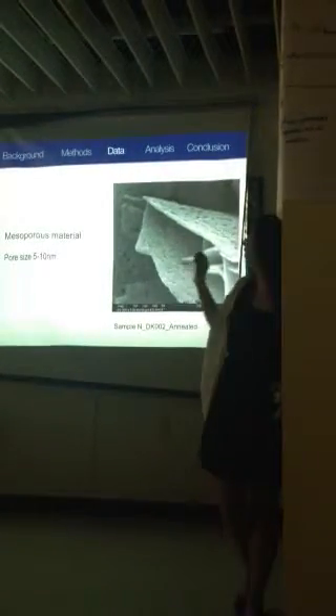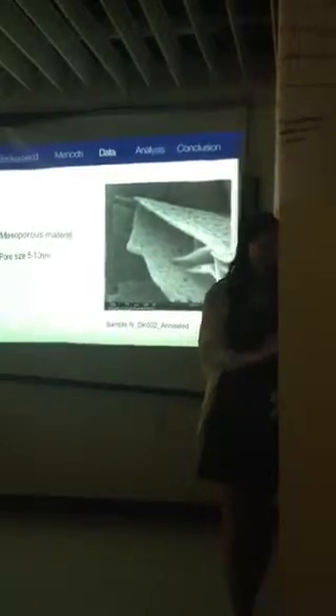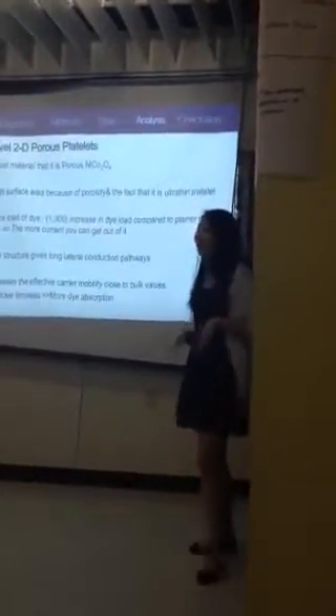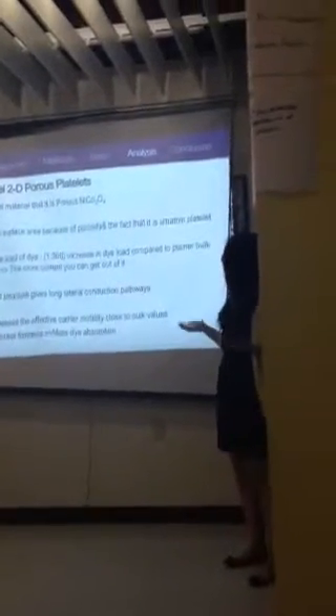These SEM images also show the platelets I got. I don't know if you can see on this slide well, but you can see a perfect hexagonal structure platelet right here. Perfect hexagonal structure right here. This means that it has really, really high surface area because of the pores and the fact that it's ultra thin.